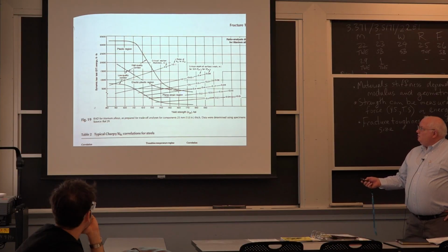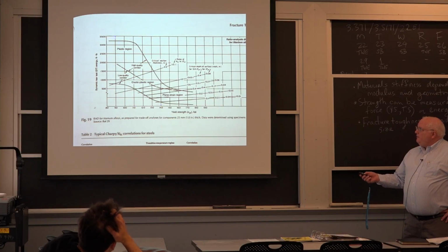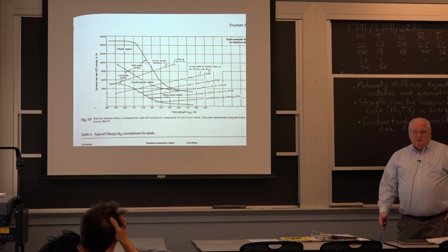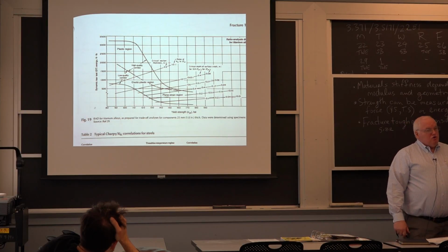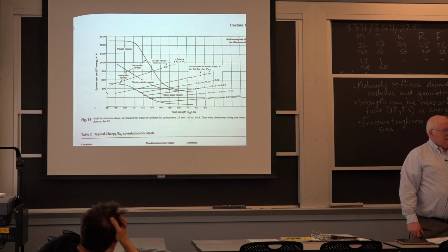The Soviets built one, or actually built several. But anyway, here's the titanium alloys ratio analysis diagram. It doesn't go out to 300, it goes out to 170, and it has the same general plot. Plastic region, elastic plastic, plane strain. And again, in the plane strain region, you're talking about millimeter, half millimeter flaws that could cause the whole thing to fail. So you can go to very high strength metals, but they're starting to act a little bit more like ceramics, so far as that goes. So you're giving up something in terms of the ratio analysis diagram.